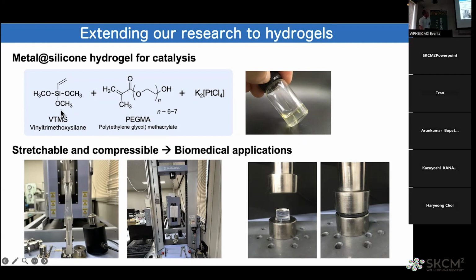So this is one example. We are now preparing a gel from vinyltrimethoxysilane, and this is the co-network of methacrylate precursor. So these two precursors form a double network, and we can prepare a nice gel. And also, we can put metal species. In this case, you can see here platinum. Platinum can coordinate to the vinyl group here. And also, if you have diphenylphosphine groups or pyridyl groups, you can accommodate palladium metal to the coordination sites. So in this way, now we can prepare hydrogels containing catalytically active complexes in the network.